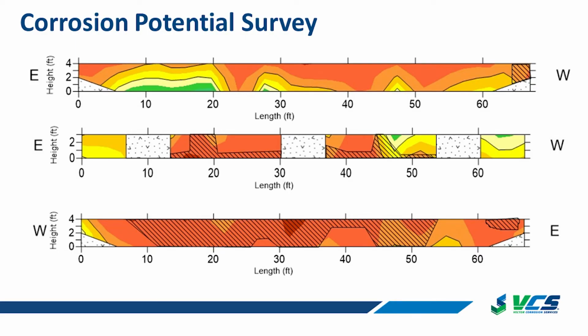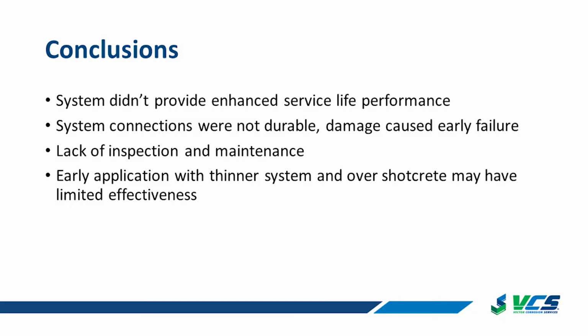So we went and corrosion potential surveyed all of the substructure. And this structure was very actively corroding. Those warm colors are high probability of active corrosion. So most everywhere on that pier cap on Pier 1 is actively corroding. And the columns were very much the same. So this bridge was very severely deteriorated, had a lot of chloride exposure over the years, and really hasn't been maintained since 15 years ago. So that's again a driver for why this bridge had to be replaced. And so, again, it puts it at a disadvantage. In conclusion on that evaluation of the CP system, unfortunately, it didn't really provide an extension in this situation.